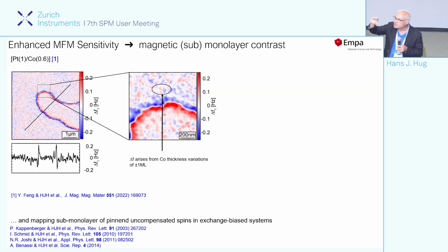The thickness actually varies. And also the anisotropy axis of the grains of this polycrystalline film varies, and that generates a noise in the stray field, and we can pick it up. First you're surprised, you're improving your measurement, and then you end up, oh, I see a new kind of background here. And then you need to understand it.